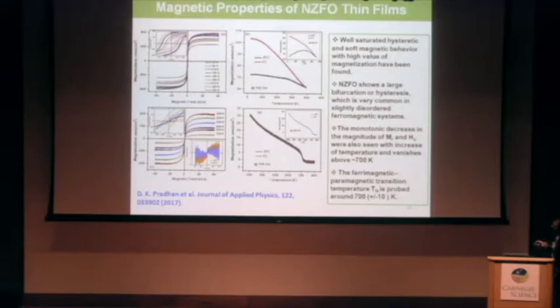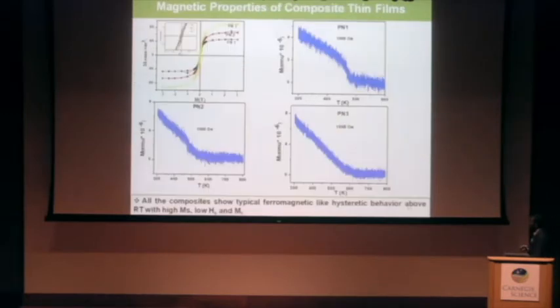And here, in the high temperature magnetization versus temperature curve, we found the magnetic transition, the ferromagnetic to paramagnetic transition, probed around 700 Kelvin. That's why we have included this nickel zinc iron oxide as a magnetic candidate in our composite structure.